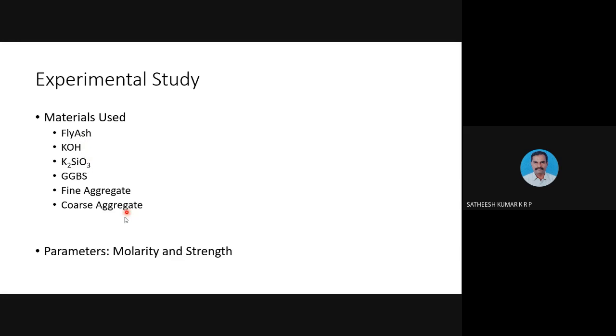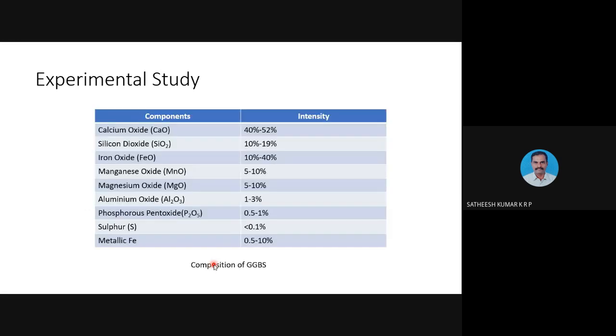We were trying to find the relation between this molarity and the strength throughout the study. And the composition of the GGBS was also found using a chemical test for oxides. Like you can see here, all these are oxides. So we found that the GGBS contains a maximum of calcium oxide and an equal concentration of silicon dioxide and iron oxide. But there are also traces of sulfur and phosphorus and some form of metallic iron, which is not significant.